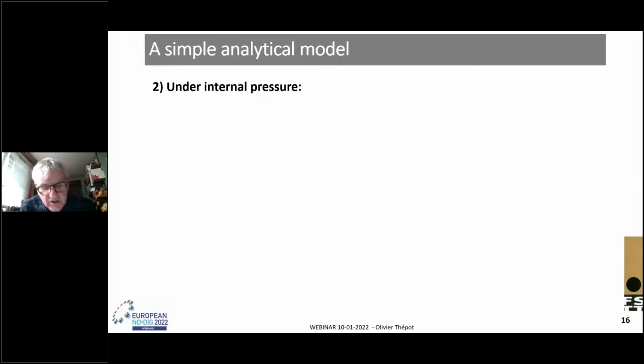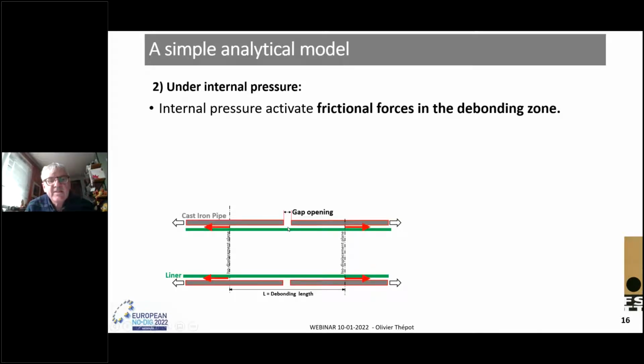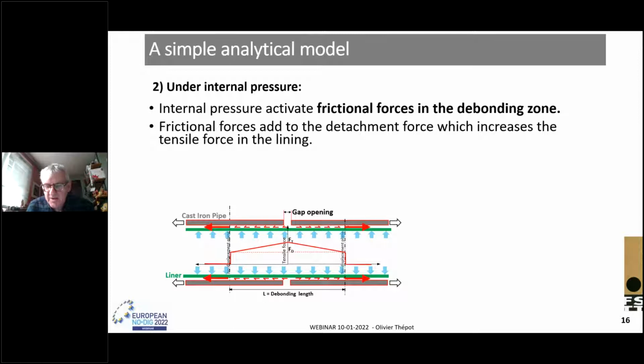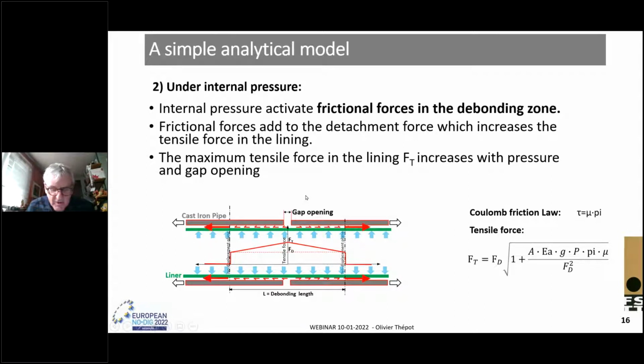Under internal pressure, friction forces are activated in the debonding area. Frictional forces add to the detachment force, which increases the tensile force in the lining. Combining the Coulomb law for the pressure-friction relationship with the Hooke law for the stress-strain relationship, it is easy to calculate the maximum tensile force, which increases with the internal pressure and the opening gap. The formula is on the right.